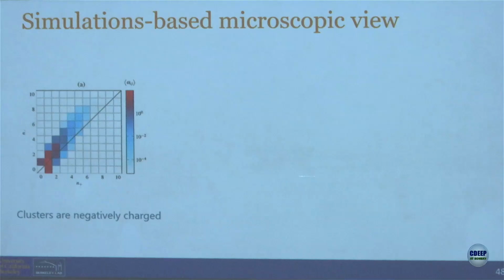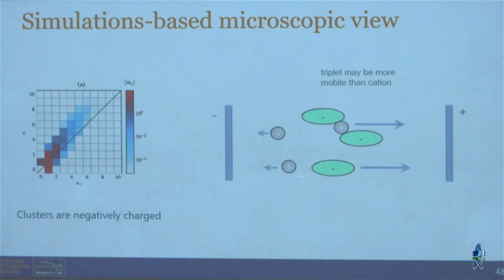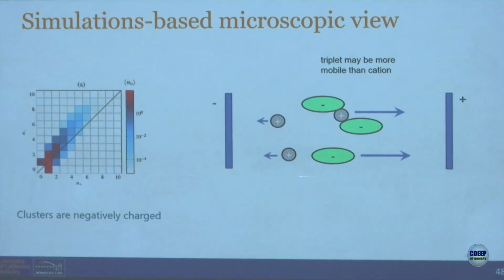The answer that they gave for this negative transference number is that when you look at clusters and analyze your simulations, the majority of the clusters are negative. This is a population. You're used to seeing dark colors mean high probability. This is n minus, the number of negative ions in the cluster, and this is positive ions in the cluster. You can see it's all skewed above this line. This is actually the classical picture of negative transference numbers dating back to the 1900s.